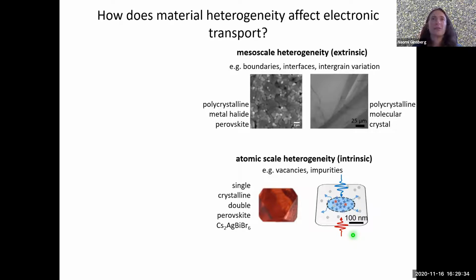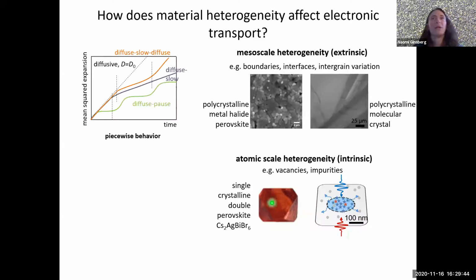And I should just say that we typically expect charge carriers to diffuse in a semiconductor because they scatter, as opposed to traveling ballistically. So rather than always measuring a straight diffusive curve in the mean squared expansion versus time, we expect that transport behaviors, when you have heterogeneities on these mesoscopic scales, might appear piecewise, as energy encounters different regions in space. So for example, this sort of start-stop behavior with these terraces here.